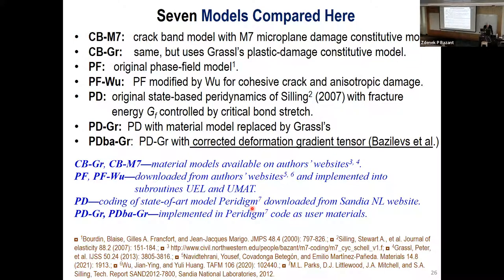So I compare seven models. Crack band with M7. Crack band, and we put on it the best tensorial model with loading surfaces invariance for concrete. I believe it is Grassl. I think it is better than our old models at Northwestern. So that was then implemented here. Then we have the phase field model, the original I described, and the improvement by Wu, which I also mentioned. And peridynamics, the original model by Silling, with fracture energy control by bond stretch. And then we took two more models.